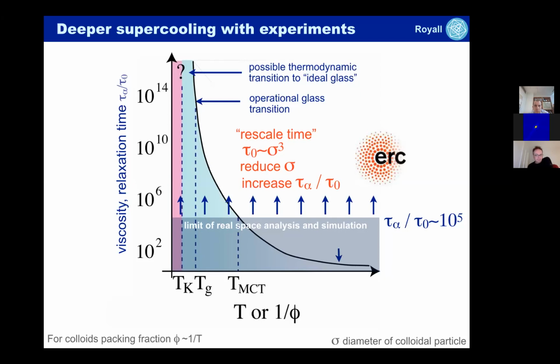But for the colloids, the time scale depends on the cube of the diameter. So I've noted the diameter of the colloids here as sigma. If I make the diameter smaller, the time scale of the system decreases, and it decreases fast. It's the cube of the diameter. So if I make my particles 10 times smaller, then they move 1,000 times faster. It is as if time accelerates for the system by a factor of 1,000.